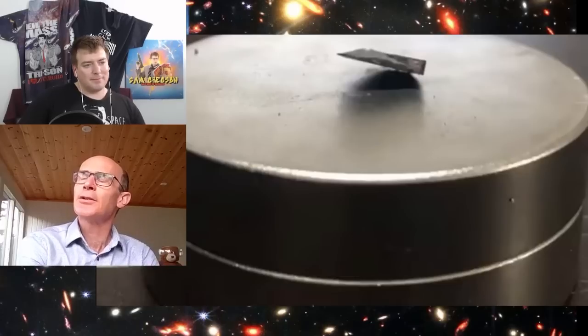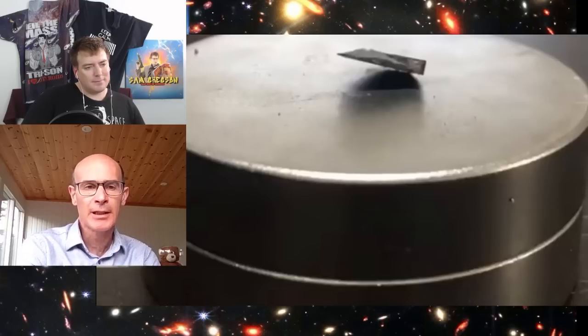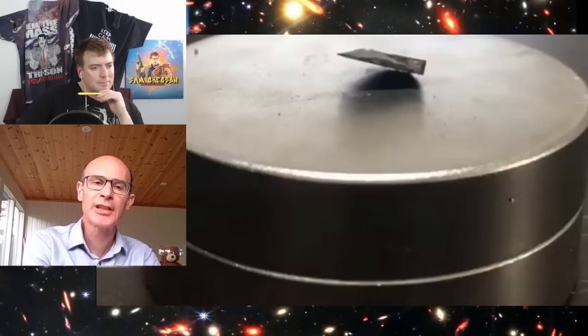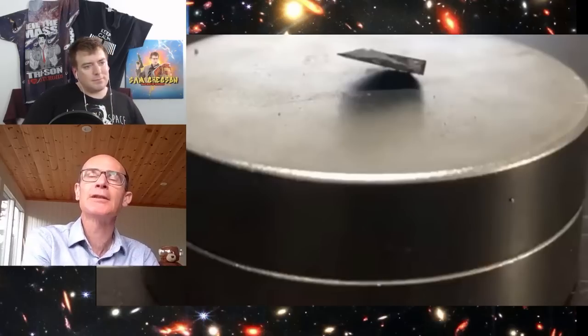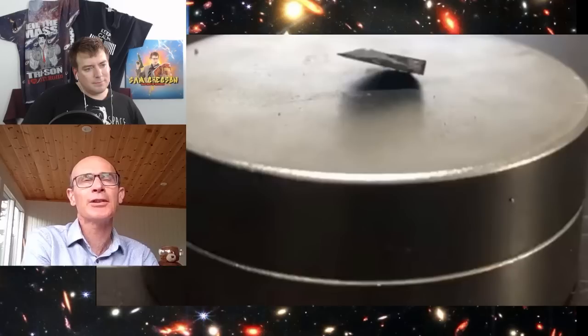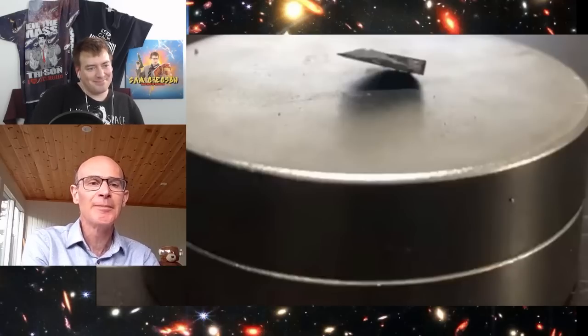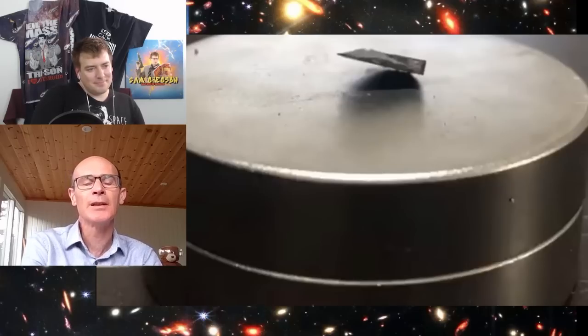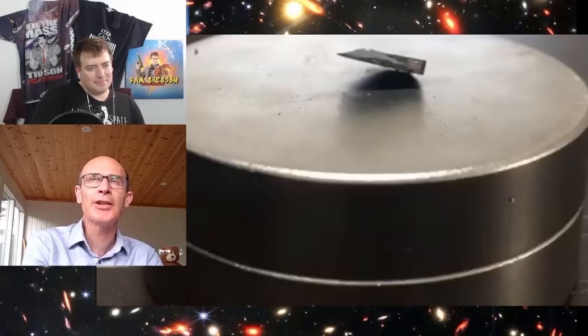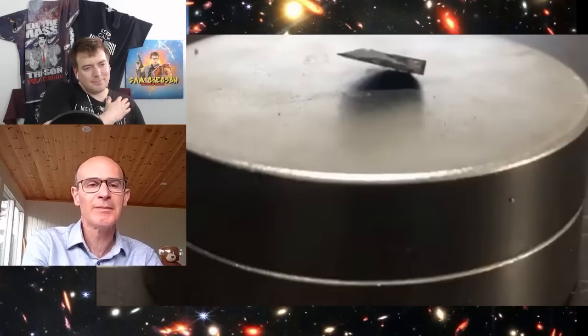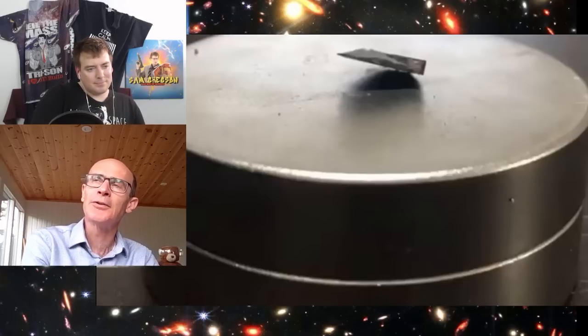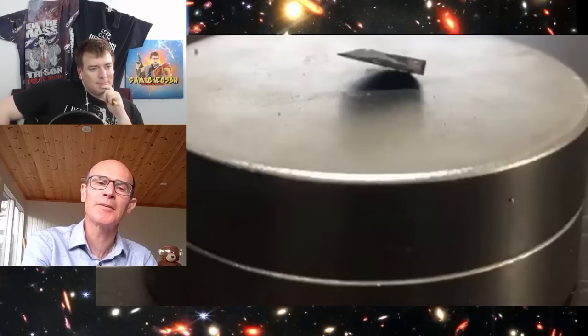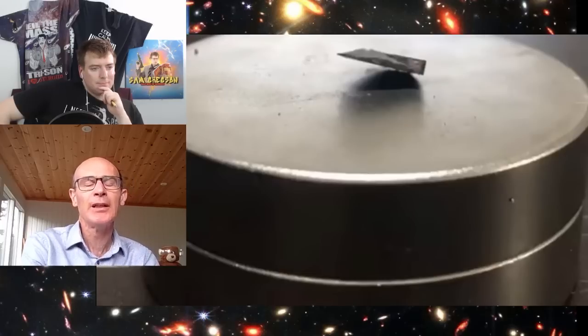Yeah, I mean, the iron arsenide story is quite an interesting one, because the effect was originally discovered in a lanthanum iron oxyphosphide. And the superconducting transition temperature was relatively low, about 4 Kelvin or something, and that was published. A TC of 4 Kelvin is not particularly remarkable. A lot of metals become superconducting at that temperature, and there was quite a lot of skepticism from experts that this was a new class of superconductor, partly because iron compounds you would expect to be strongly paramagnetic or ferromagnetic. So I do remember some people were quite skeptical that it was really the sample that was claimed that was the superconductor rather than some impurity.